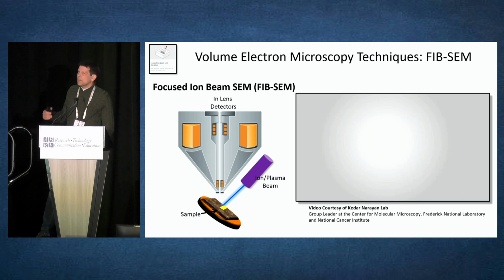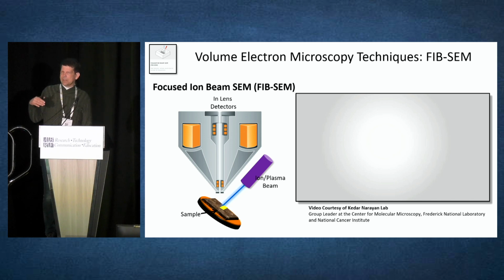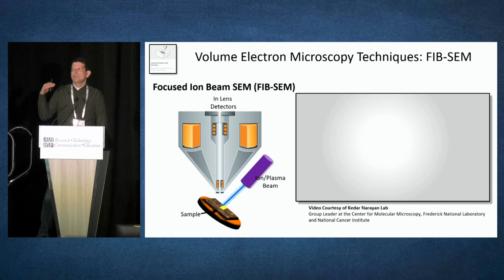All right, so now I'm going to move into FIB-SEM. I think I'm on good cadence here, so we'll get through it. So, focused ion beam scanning electron microscopy. The reality is that when you use a diamond or physical cutting, you really can only get down so thin. It's a matter of physics. 50 nanometers, 20 if you've got a really perfect sample, but more like 50 to a little bit higher. But the ion beam is cool because you can shave just a few nanometers at a time.